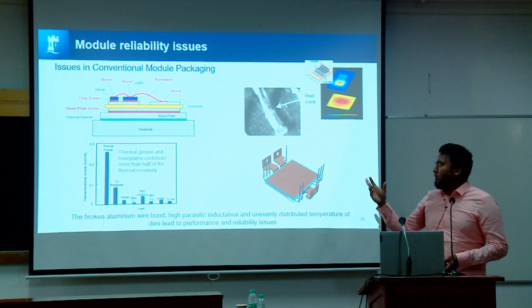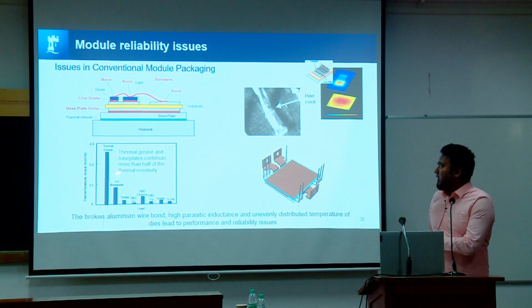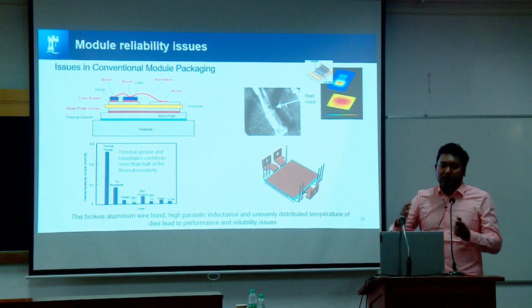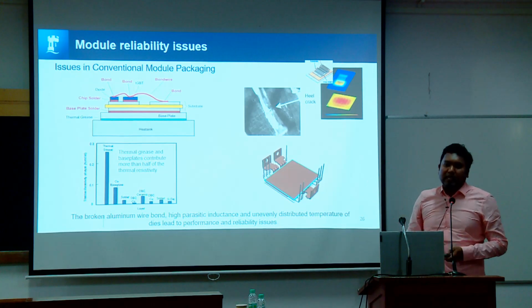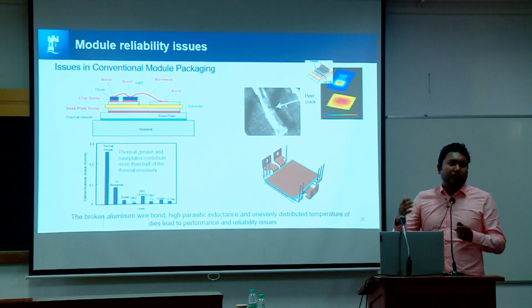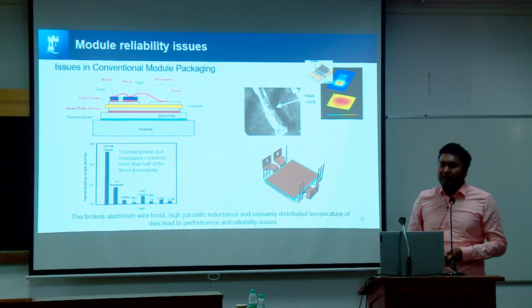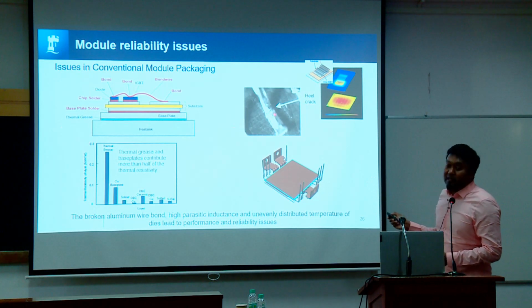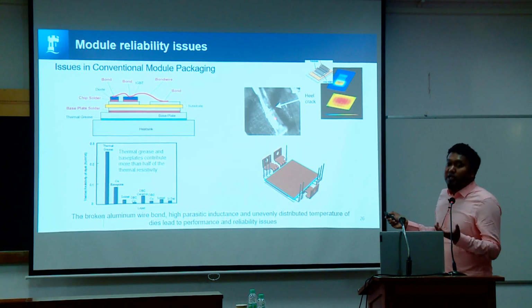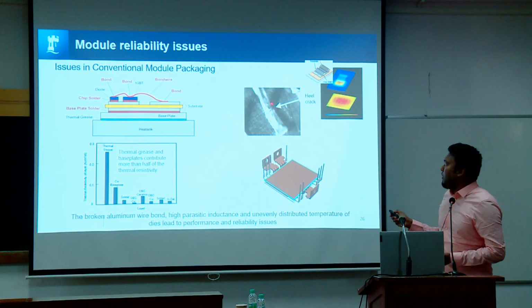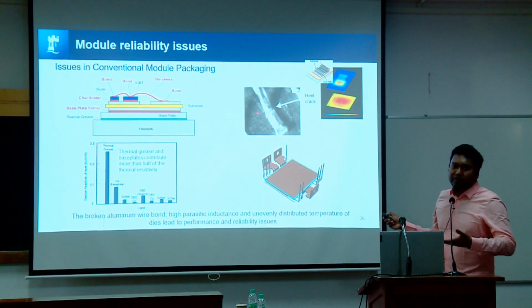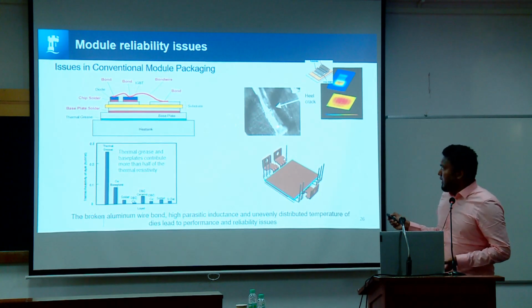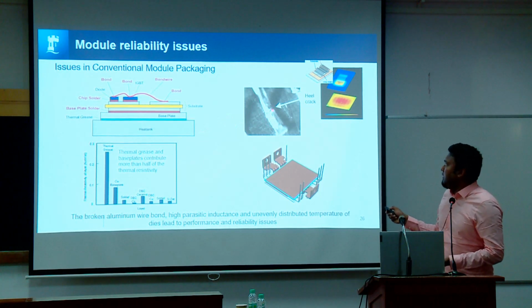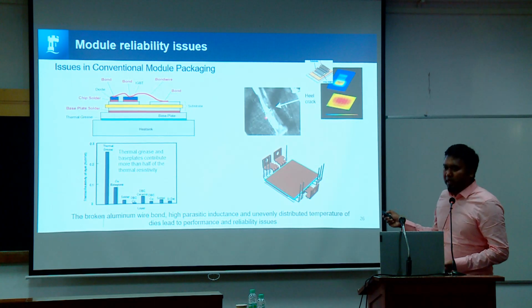So what will happen if you have a high delta T? Obviously all these materials will expand and contract, expand and contract. And if they don't expand and contract at the same rate, you will start seeing cracks at weak points. In these modules, the weak point is the heel of the wire bond. We have run accelerated life tests, we've x-rayed this module, and we can see the heel crack here.